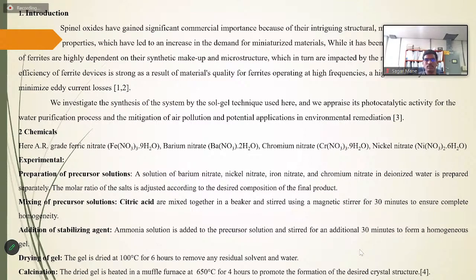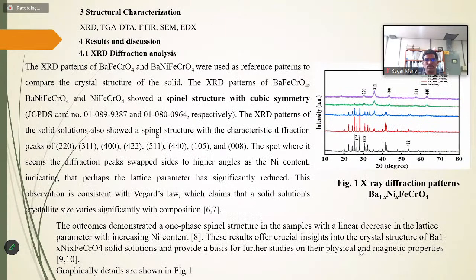Then structural characterization. During this presentation, XRD, TGA, DTA, FTIR, SEM and EDX are the characterizations utilized for this particular compound. In the XRD pattern, we reveal characteristic diffraction peaks at 220, 311, 400, 422, 511, 440, 105, and 008, which we observe here. Spinel structure with cubic symmetry can be confirmed by the 311 peak.